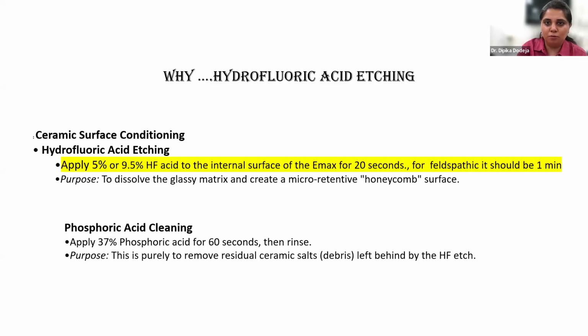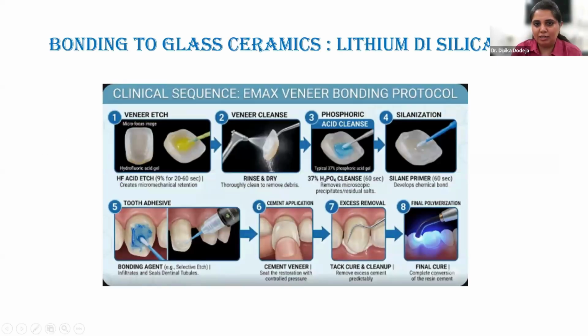Okay, so this is the sequence for your EMAX or your lithium disilicate glass ceramic. First is your hydrofluoric acid application for 20 seconds. Wash it. Then you put phosphoric acid to remove the residual salts for 60 seconds. Wash it, dry it. Then you apply a silane coupling agent. Let it react for 60 seconds. Then you air dry it. This completes your preparation for the ceramic. Then you move on to the tooth where you do your etching of the enamel and dentine, 30 and 15 seconds respectively. You apply your selected bonding agent, light cure it for 10 seconds, not more. Load the veneer with the cement and place it with a passive pressure. And you can tack cure it after that, remove the excess cement, and then the final polymerization, which is 40 seconds on every surface.